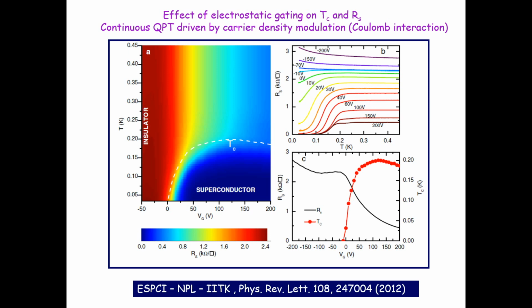On the negative side, you drive the superconductivity out, and you end up with a sort of dirty metal whose sheet resistance in this limit of temperature is still lower than the quantum resistance for localization in 2D. That's why I'm calling it a dirty diffusive metal. And it turns out that the behavior of the sheet resistance as a function of gate voltage is actually not monotonic. On the positive side, the sheet resistance changes pretty fast, and the negative side is almost like a plateau.